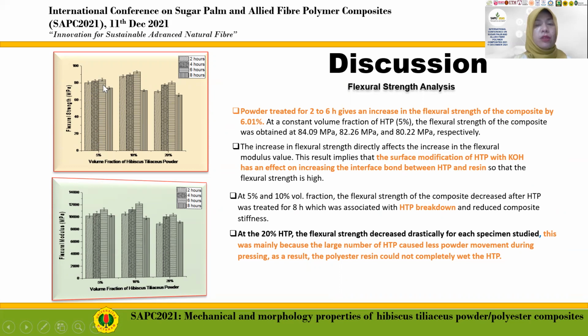The increase in flexural strength directly affects the increase in the flexural modulus value. This result implies that the surface modification of hibiscus powder with potassium hydroxide has an effect on increasing the interface bond between powder and resin so that the flexural strength is high. At 5% and 10% volume fraction, the flexural strength of the composite decreased after the powder was treated for 8 hours, which was associated with the powder breakdown and reduced composite stiffness.